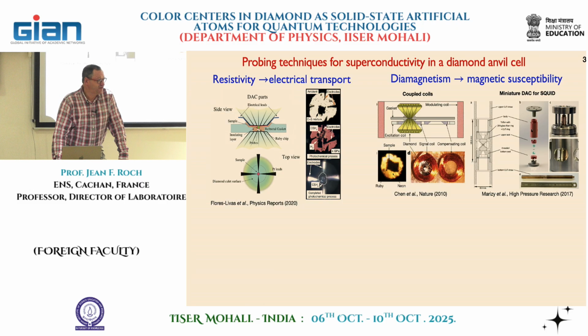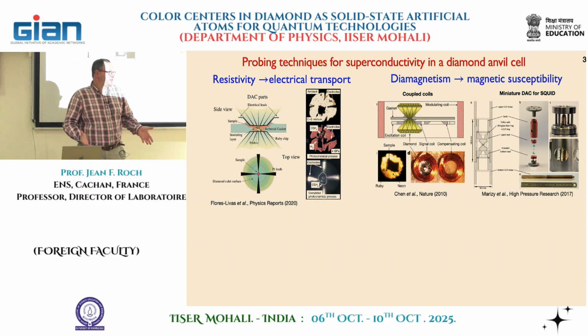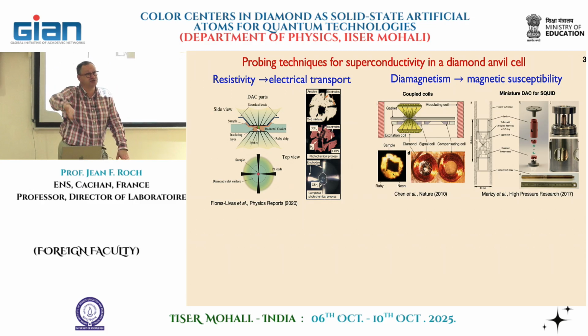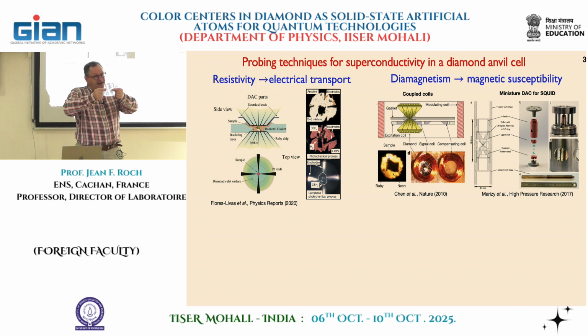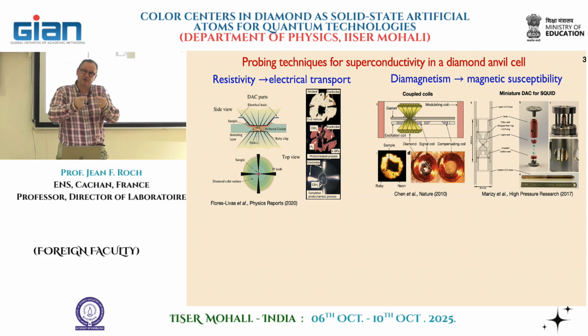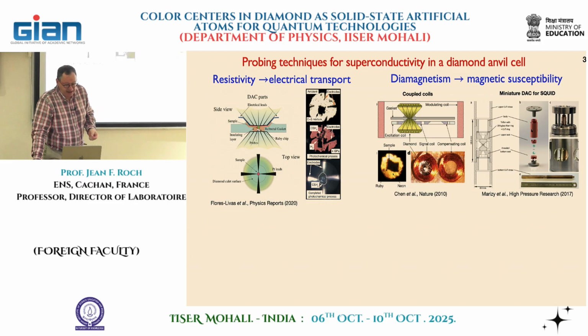Now, what you want to have also is diagnostics. You want to measure that your sample, due to the pressure that is applied on it, becomes a superconductor. So, of course, you have one approach. It's to put electrodes and measure the transport properties, the resistivity of your sample, and you should see that it drops to 0. You can imagine that you have now to put very tiny electrodes. You need 4, for instance, to avoid any bias in your resistivity measurements, and that will go onto the sample. And this is very difficult.